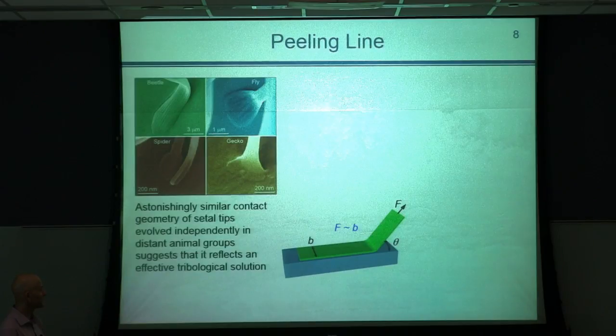So if this is the duct tape that I just mentioned, the force that you need to apply in order to peel it from the surface will depend on 3 parameters. One, the angle. If you try to pull it in the direction of the film, it will hold well. If you peel it in the opposite direction, it will detach very easily. So angle is important. The second parameter is, of course, the chemistry of the interface. And it also depends on the width of this film. So the contact area is not really important. What is important is the width of this film that determines the force.